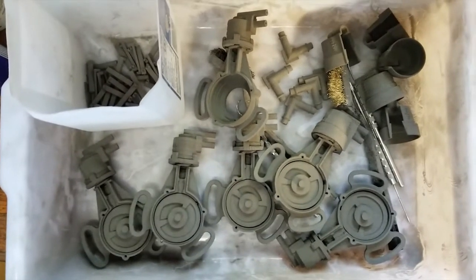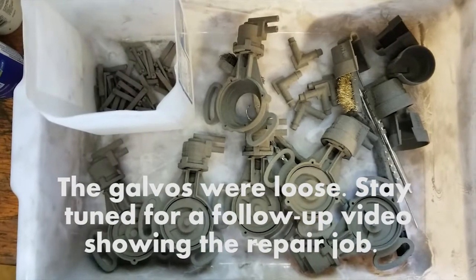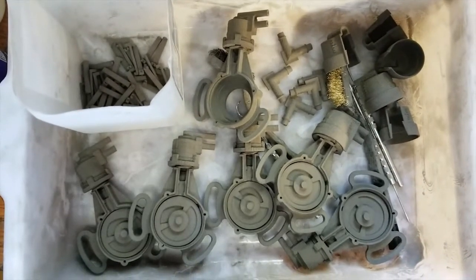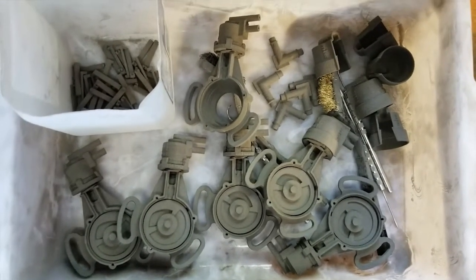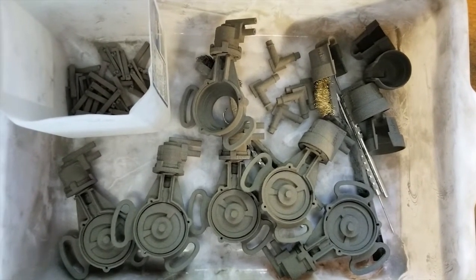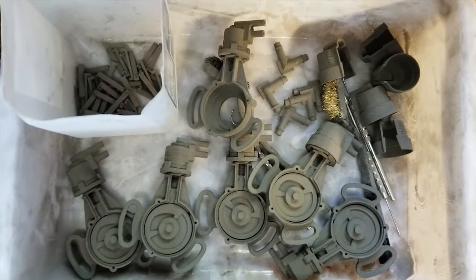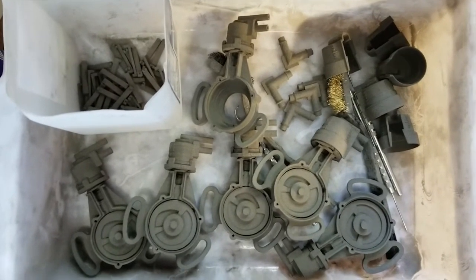So I think I've got this thing tuned in. I'm going to check my galvos to make sure they're not just a hair loose because the issue was near the top. I had some mismatch on my hatch — about less than a half millimeter on just a handful of parts. So maybe my galvo is loose, or maybe the patterning doesn't really work that well once you get over a thousand layers. That could be another issue.